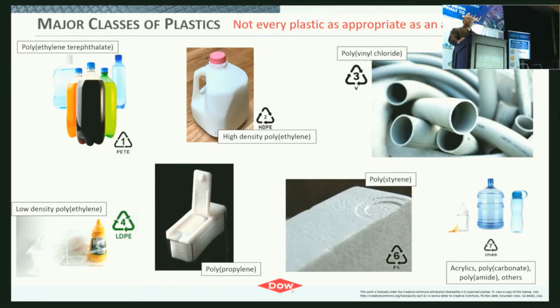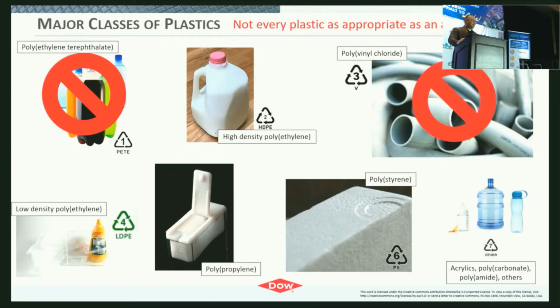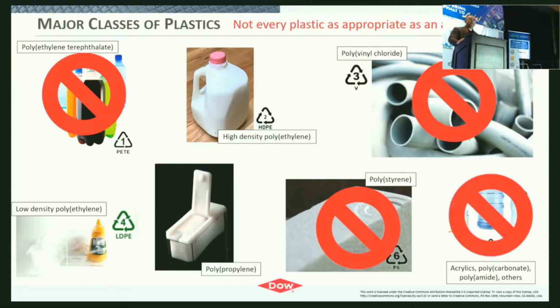And just with the caveats here, this would be considering a wet process, like how we mostly traditionally use polymers to modify. Also, no chemical treatment post-recycling, but just as is. And so polyethylene terephthalate has a melting point about 100 degrees C above compaction temperatures. PVC can potentially off-gas. Polystyrene has a high melt point. And then the others are a mixed stream. And because we really want to have a known modifier coming in, these get deselected.